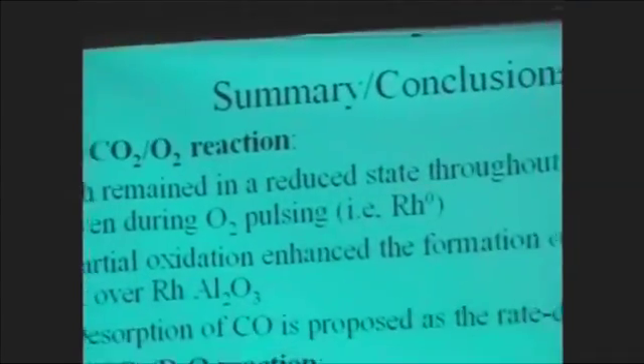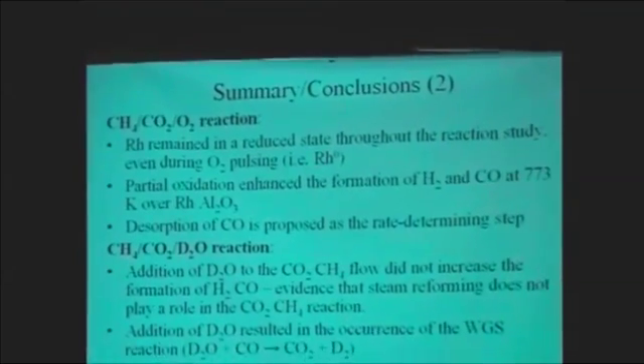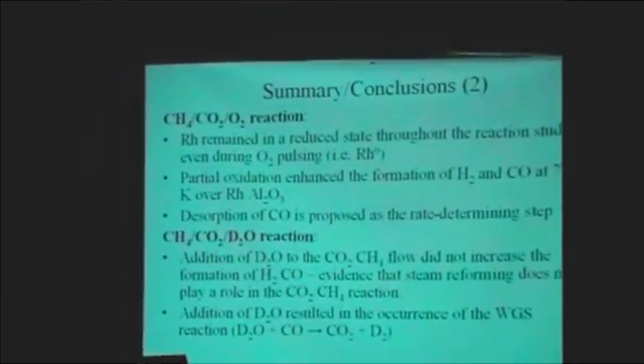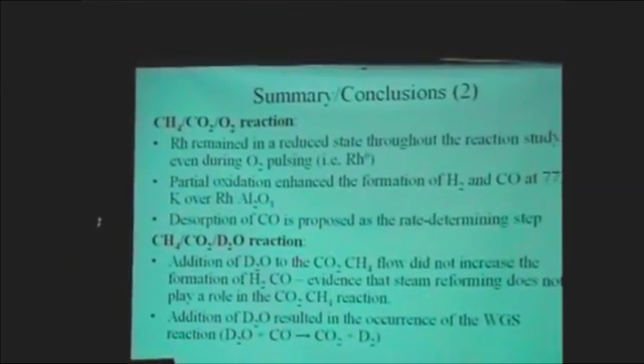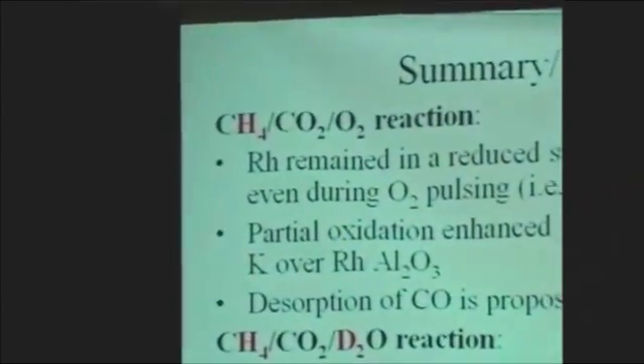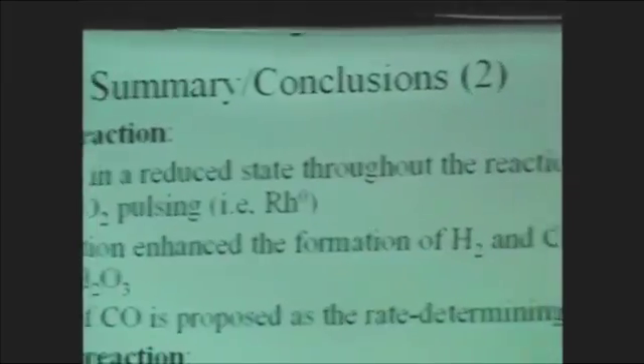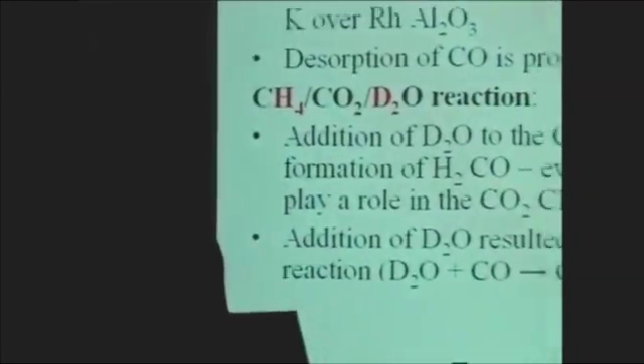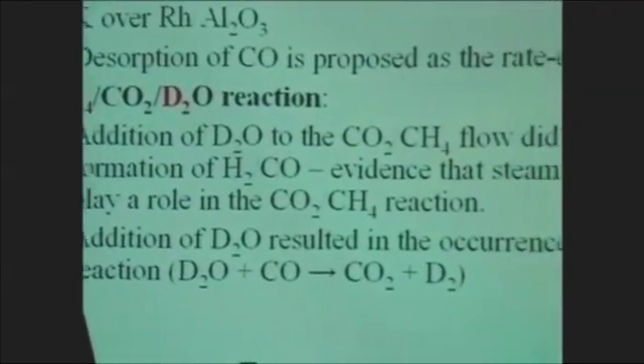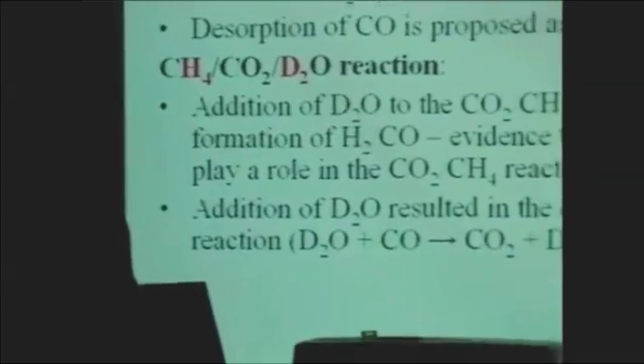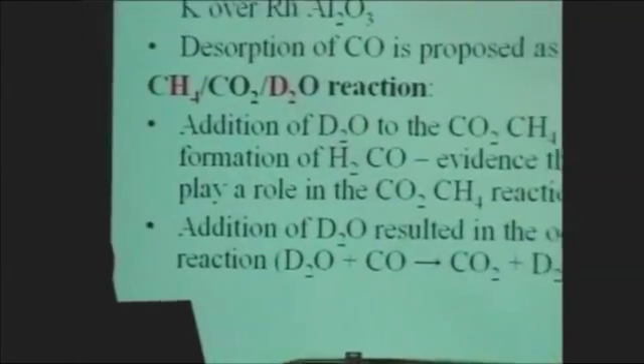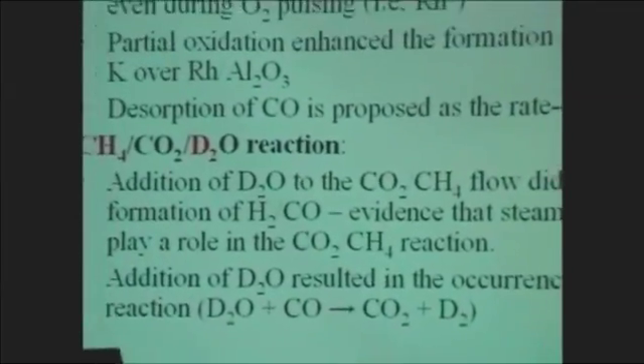So at the end here, we can enhance the formation of hydrogen by putting the oxygen in, and we can pulse the oxygen to control the amount of oxygen into the reactor to promote the formation of hydrogen. But at this moment, we really didn't fine-tune this technique yet because we are not quite interested in methane reforming, so that's why we didn't continue this work. This work basically stopped at this point.